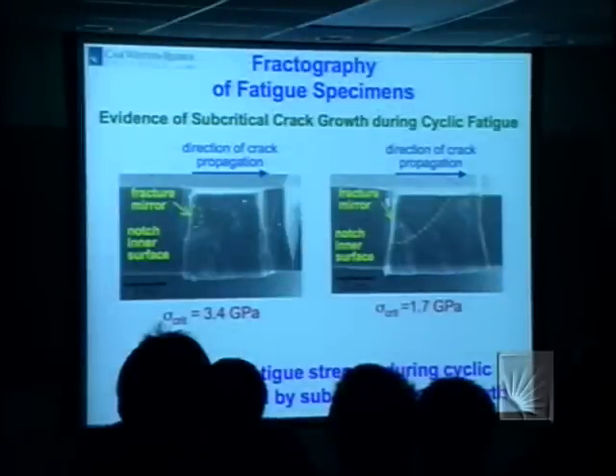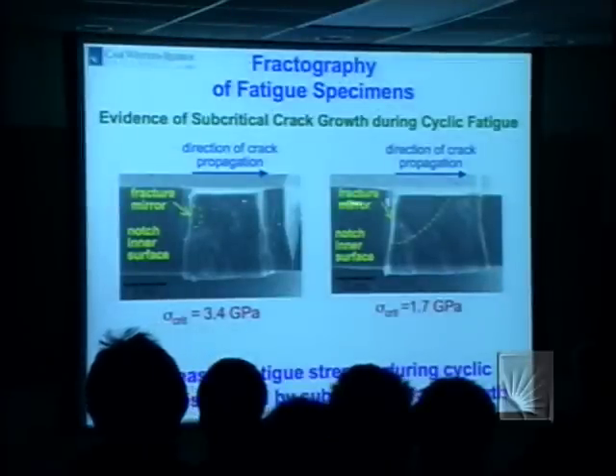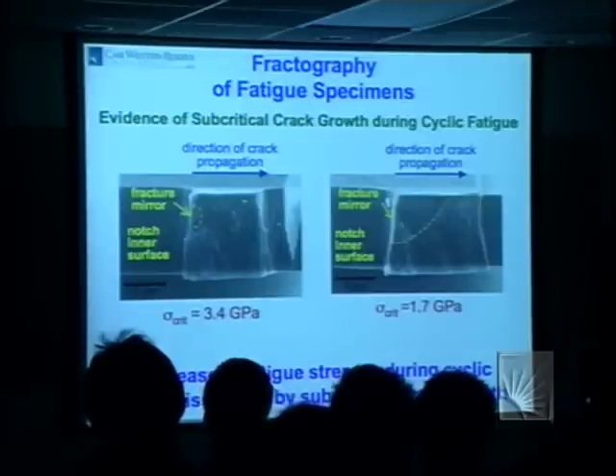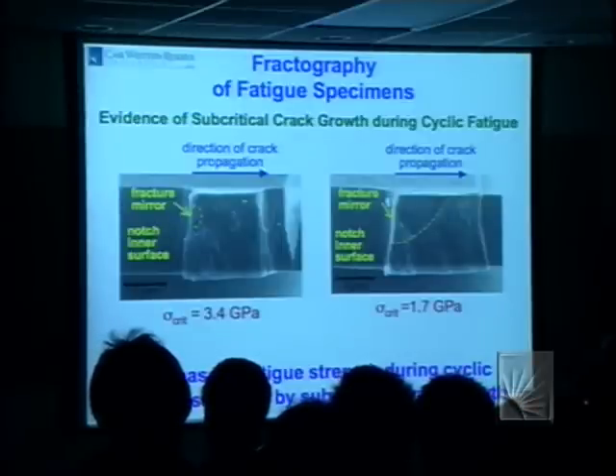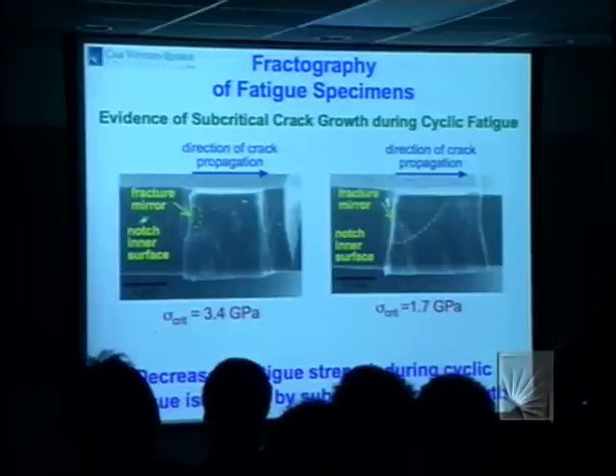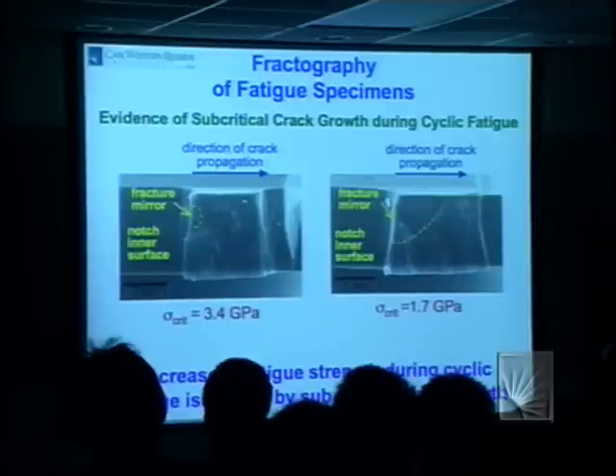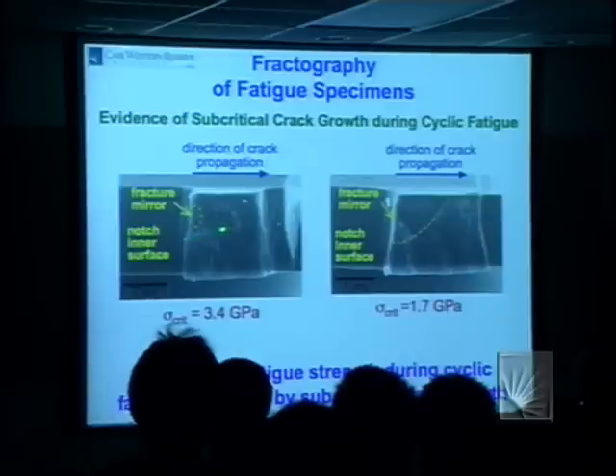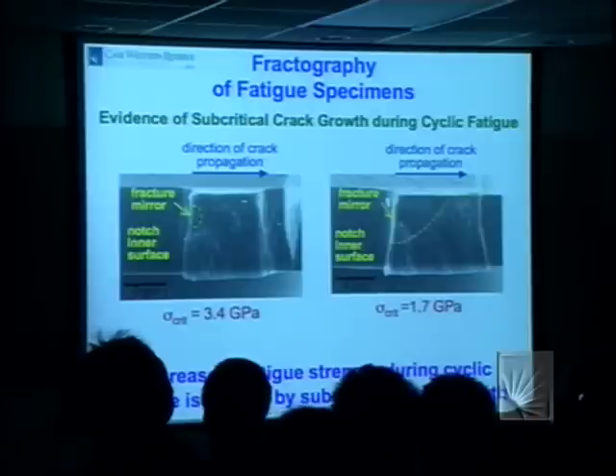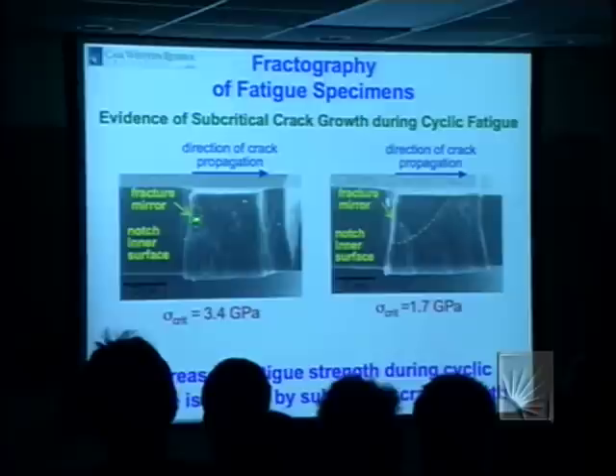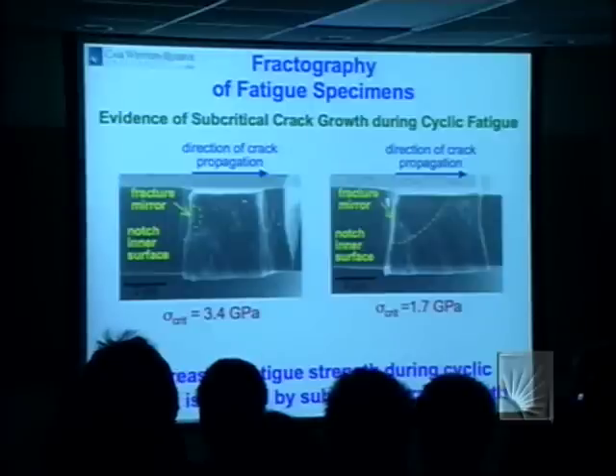And to understand what was causing failure at the lower stresses at the longer times, we resorted to a ceramic trick. This has been well known mostly in the glass field. When you look at a fracture surface, what you invariably find for brittle material is that there's a failure point somewhere here, and then there's a region where you get a very flat fracture surface. That's called a fracture mirror.